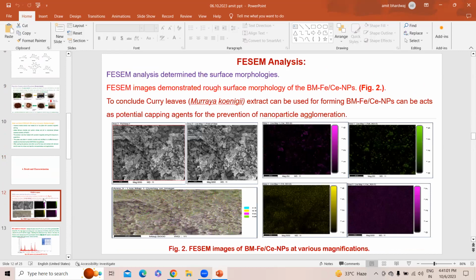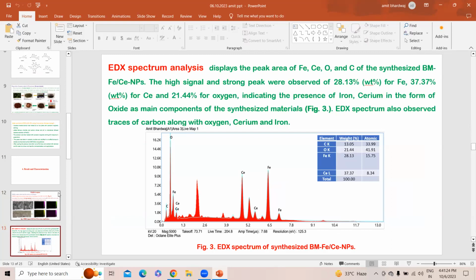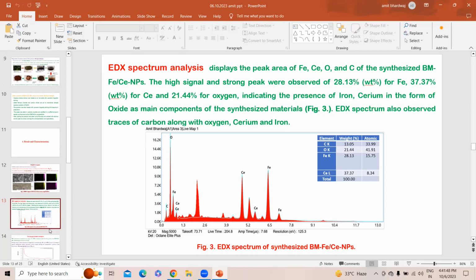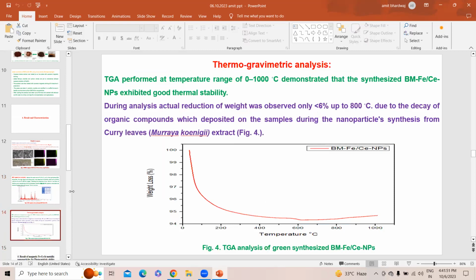The first characterization was FESEM, field emission scanning electron microscopy, at IIT Roorkee. This characterization shows that the plant extract acts as a potential capping agent for the prevention of nanoparticle agglomeration. Then EDS analyzes the composition of the nanoparticles present in the material: 28.13% iron, 37.37% cerium and 21.44% oxygen, along with carbon combined with oxygen, cerium, and iron.